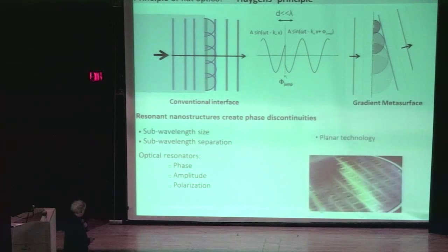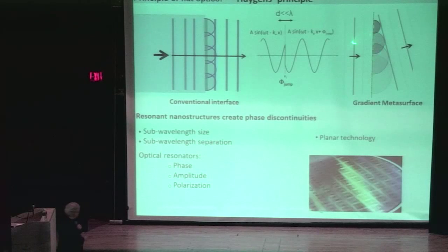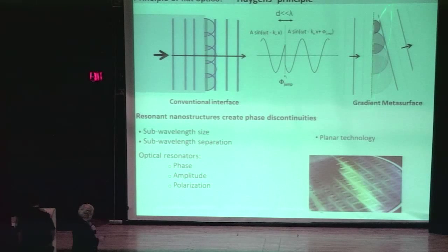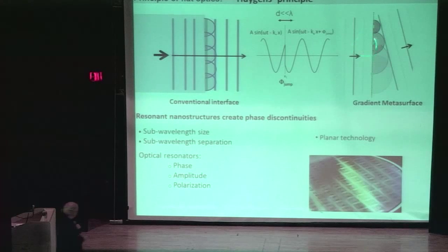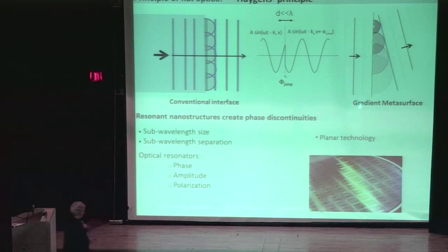And then a tougher question, if we claim that metasurfaces can really do good for technology, we have to show some kind of instrument function, going beyond the single component. And I'm finally going to give you one recent example of this, where we have made a polarimeter, which works as well as a state-of-the-art polarimeter that you can buy, but it's much more compact, simple to make. And I think this is one interesting direction for metasurfaces. And finally, some science on new metasurfaces where we use disorder. So this is basically an old slide, but it tells about it. If you decorate a metasurface with a bunch of resonators here, depending on the resonator design, you can design the wavefronts that are coming off and then using Huygens' principle, you can intuitively predict the wavefront.